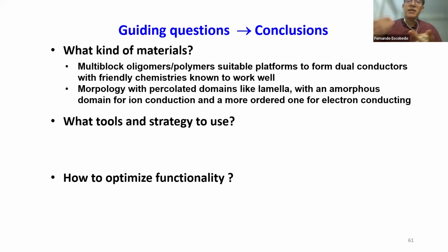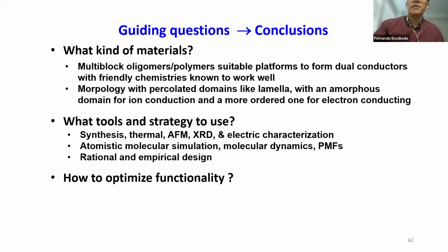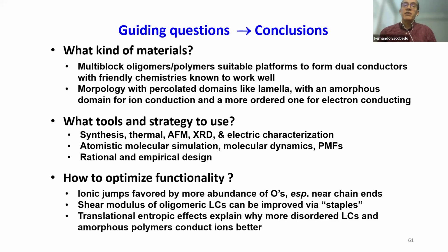So the first two are basically just the reasons why we chose the materials we want to study, the tools that we use to try to understand and characterize the systems, and that to optimize the functionality. So we want to have more ionic jumps, which are favored by a more abundance of oxygen, but especially near the chain ends, and that the shear modulus of these small liquid crystalline materials could be improved by staples, for example.